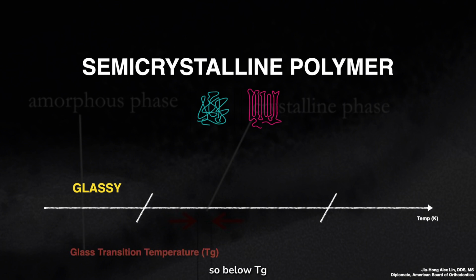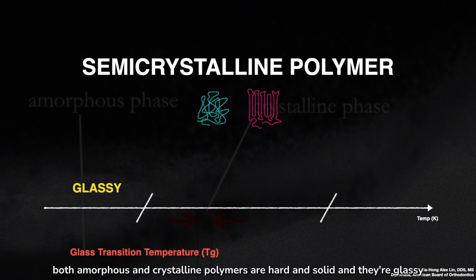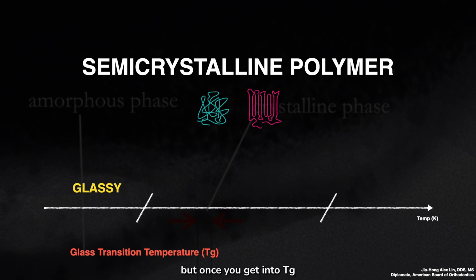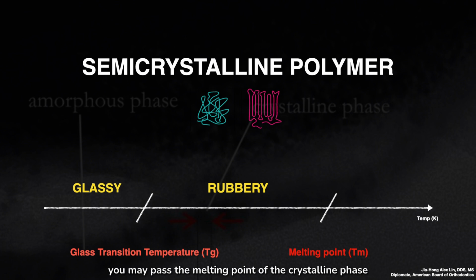So below Tg, both amorphous and crystalline polymers are hard and solid, and they're glassy. But once you get into Tg, the amorphous polymer starts to loosen itself, and then the whole thing becomes rubbery. If you raise the temperature even more, you may pass the melting point of the crystalline phase, and then the whole thing becomes liquid. Now, sometimes it may actually decompose, but just remember, once you pass the glass transition temperature, the amorphous part becomes rubbery.